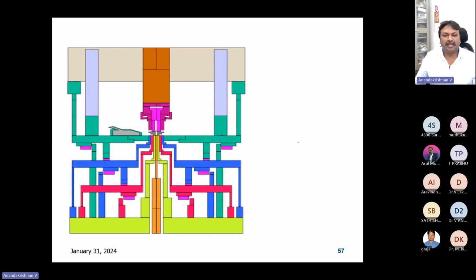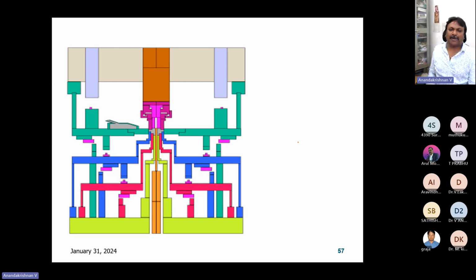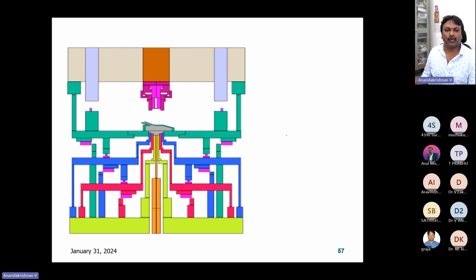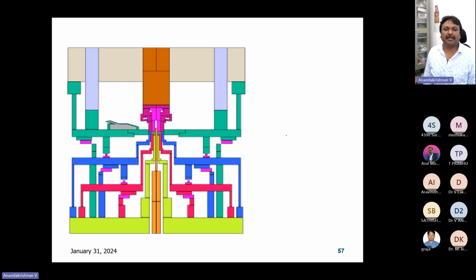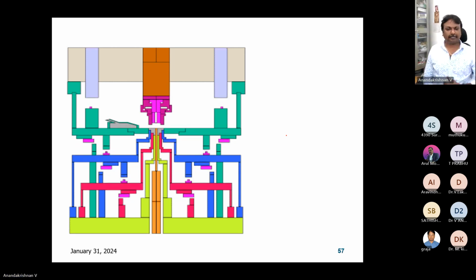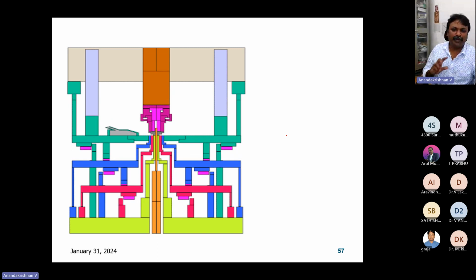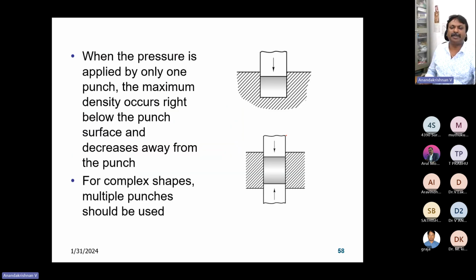This is a conventional powder metallurgy compaction and sintering process, where a shoe fills the powder inside a container, a die, and there are relatively moving parts, right? You can see over here. Why? Because if you apply pressure on a static powder from the top, the density will be a little higher at the top and poorer at the bottom. If you apply movement from both the top and bottom, you still have density variations along the axis. It is higher density at the top and bottom, and in the middle we may get poor densification.